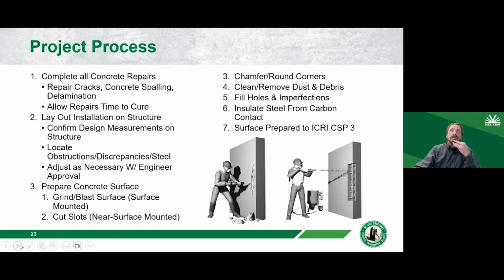Then once it's time to do the installation, we grind or sandblast the concrete to get it clean, or cut slots for the near surface mounted laminate strips. One of the issues that we run into is that anytime we encounter a corner and we are wrapping around it, we have to make sure that we chamfer and round the corners, typically 3/4 of an inch, 20 millimeters, to ensure that the wrap is intimately adhered to all parts of that concrete. And then we start installing the FRP.